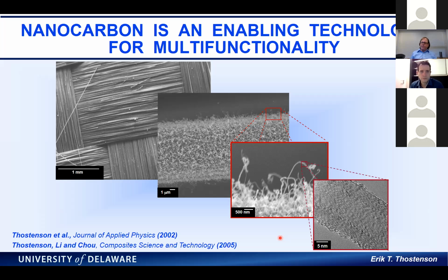Do you usually use a single fiber fragmentation test for the interfacial adhesion, or do you use other tests as well? Here at the center, we do almost every interfacial test. We've done fiber push out, and we do microdroplet. Years ago, they did fiber pull out, which is really sort of microdroplet, but on a different level. And then also fiber fragmentation. I knew how to do fiber fragmentation, so that's why I did it. But it's nice because you can do one specimen and you get a ton of fragments.